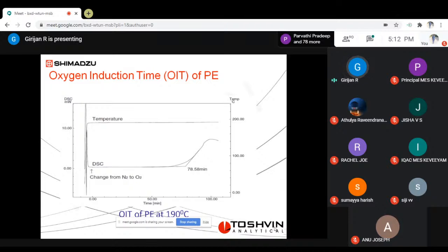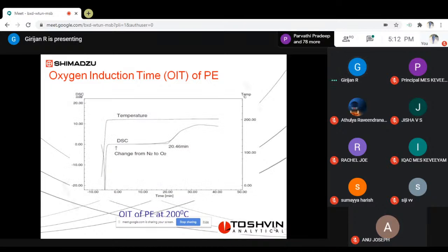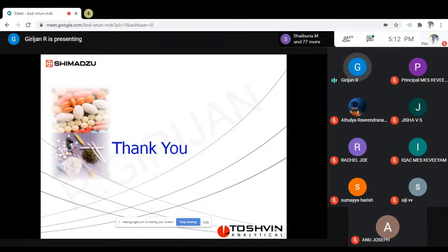Now, if I change this temperature from 190 to 200, you see the drastic change. If I heat the sample originally to 200 degrees centigrade and then introduce oxygen, you see the OIT is reduced to 20 minutes instead of 78 minutes. So the OIT also depends upon the temperature at which you introduce oxygen in place of nitrogen. As I told you, there can be provisions for introducing different atmospheres. That was my starting point. If nothing is mentioned or suggested, then your experiments are always carried out in a blanket of nitrogen, that is, a 100% inert atmosphere. And I think that is my last slide.